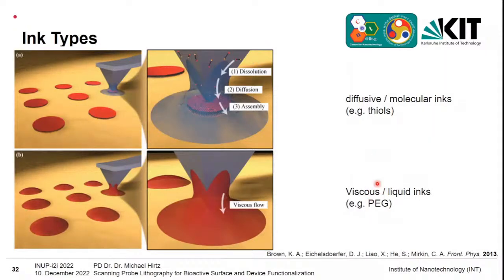In terms of more liquid viscous inks, that could be, for example, polyethylene glycol or glycerol or any other non-volatile inks. They will go over from the tip to the surface in terms of a viscous flow, and this is much harder to describe, because here you would go into the realm of hydrodynamics. But basically what you end up with is that you then deposit small droplets on the surface, and the shape of these droplets is then highly governed by the surface energies, also by the surface tension of the liquid and the surface energy of the surface.